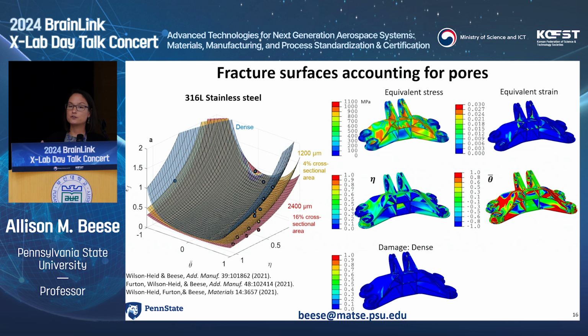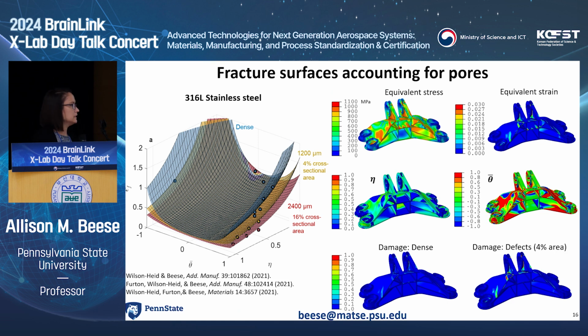The other thing, though, that we can do with this, and this is the powerful thing, is we can say, well, what if we do have defects in our material? How critical are they? So now we could say, well, I want to assume that I have defects of a certain size, so maybe this yellow surface here. And we would say, how far away from that surface am I at every location? And in this case now we see that there's a few more places that light up in red, meaning that we would be close to failure if we had pores of that size.